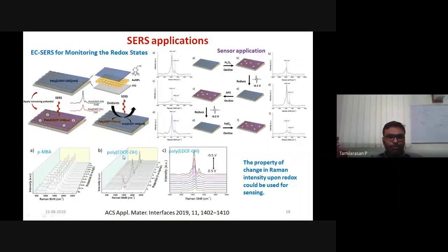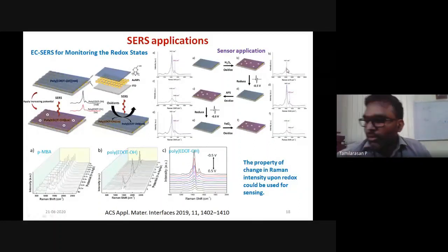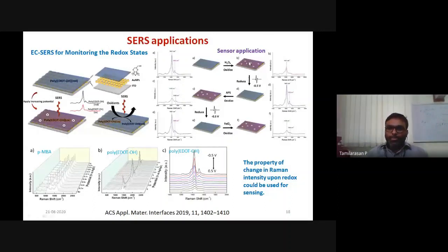So having this proof, they employed this. Initially they took a reduced form of hydroxylated PEDOT, and they put in some oxidizing agent, then it is oxidized. Because of this oxidation, the peak intensity is reduced. Once again they regenerated it with an electric signal, and they used the same substrate for identifying another oxidant like APS. You are seeing the same effect here, the drop in peak intensity, regenerate with electric signal, and once again use it for some other oxidizing agent.